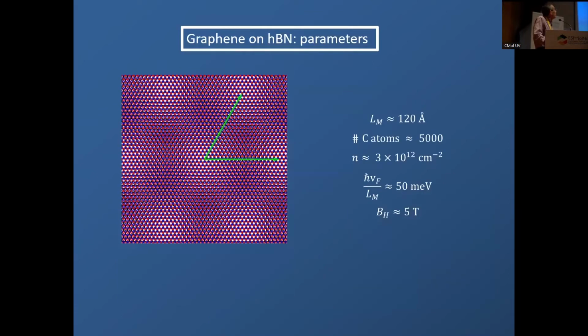And these are the numbers. So the unit cell, in the case of perfectly aligned boron nitride and graphene, has a lattice constant of about 12 nanometers. That includes about 5,000 carbon atoms. And in order to fill up one band in this periodic system, you need about 3 times 10 to the 12 electrons per square centimeter, which is reasonable.